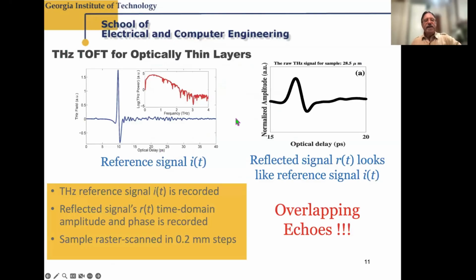Now, the key problem is what happens when the layers are thin. When the layers are thin, the different echoes overlap in time, and it looks just like one echo. So one is not able to extract the thickness of the layer when the echoes overlap, so we need to work much harder. And that's where signal processing and now machine learning comes in. This is where we spend most of our time. Usually the experiments themselves, getting the data, is not that hard. It's the analysis where most of the work lies.